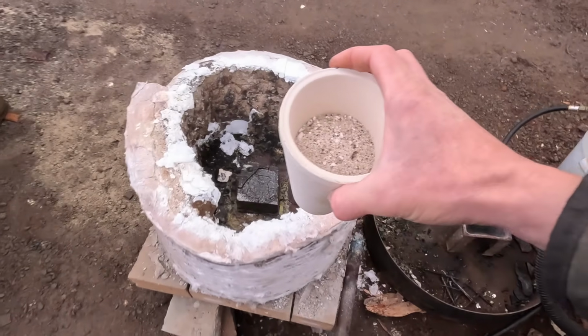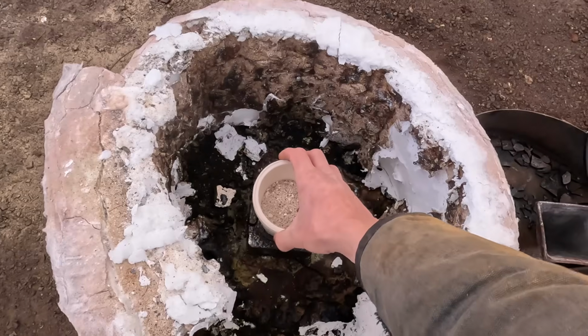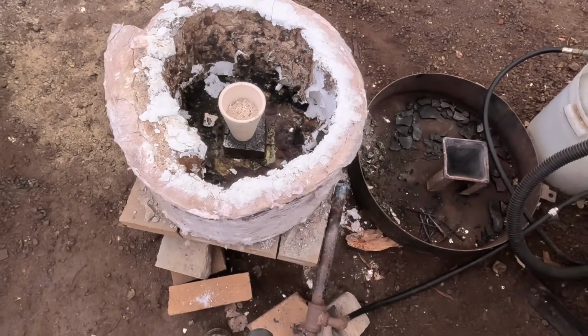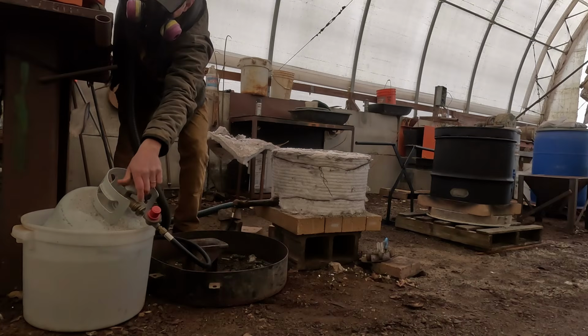Come on over here to our furnace. Now we'll get that fired up. Now, why don't I add the iron nails now is because the bismuth oxide that's in there and the potassium nitrate will also eat those iron nails. We'll use up some of our oxidizing power on the iron nails, which we don't want to oxidize. We want to oxidize the sulfides. So let's let all that oxygen get released and react with the sulfides first, and then we'll add the iron nails in at the end so we don't waste a bunch of our oxidizing power on iron.